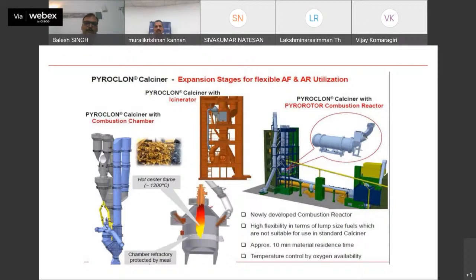If our requirement is more than that, then we can use the calciner with combustion chamber, where we can use around 50 to 60% replacement of calciner fuel. But it also has a limitation that the fuel sizes have to be controlled.